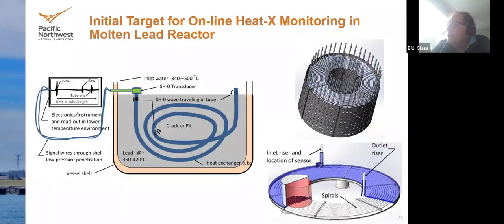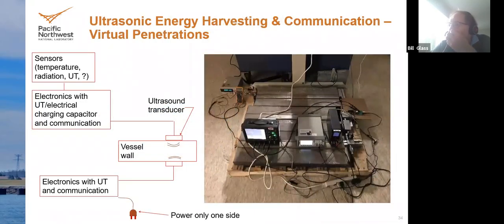So here we're back to the idea of how you will have a sensor. Here is the sensor at this end of the tube. The sensor will send a guided wave into the coiled tube, round and round and round. And ultimately, if there is any flaw or crack or pit or anomaly in the tube, some of that sound will reflect back to the sensor element here, and we think that we can make these sensors last in this particular case simply in the lead environment, where the sensor is mounted on the inlet riser, and the location of the sensor would be here, and we can send the signal all the way around the tube. So that's a current project that we're looking at.